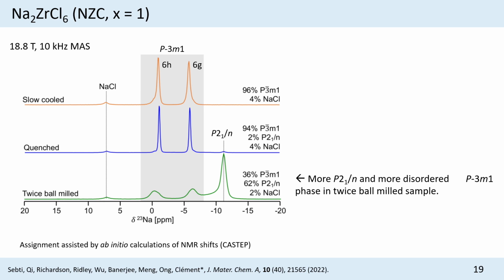And so these are NMR spectra obtained on the slow-cooled, quenched, and twice-ball-milled samples, and you can clearly see a drastic evolution of the NMR data, suggesting that the crystal structure is changing. Sorry, I have some shading here that is not shown in the slide, but both of these peaks, this peak and this peak, correspond to the P-bar-3m1 structure. You can see that it's present at 96% in the slow-cooled sample. In the quenched sample, it's also the major phase, but if you ball mill the material again, you start forming this other polymorph of NZC.